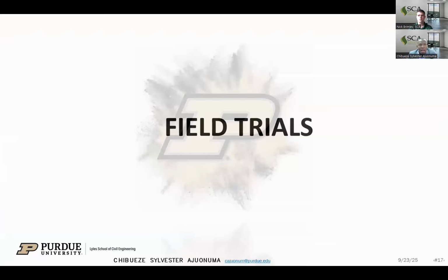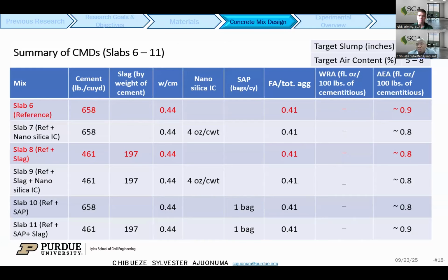And with this result, we proceeded to the field trial. The concrete requires 658 pounds per cubic yard of cement, and a constant water to cement ratio of 0.44. Our target concrete slump was between 3 to 7 inches, and our target air content was between 5 to 8%.